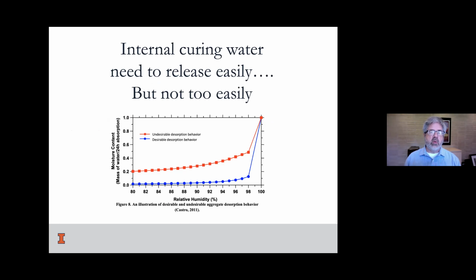And internal curing: we need to find ways to put that water in a pocket and then release the water easily, but not too easily. If it's too easy, then we haven't accomplished anything. The water is just free and moving around like it normally would. But we want to have some kind of a retention ability, so the water is held until a little bit later in the process. And you can see here where a couple percent drop of relative humidity creates a pull, a competition for the water that pulls the water back away from the superabsorbent polymer.